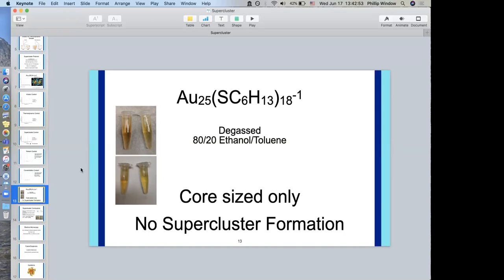So I think changing the actual nanoparticle core to something larger might reduce the effect that the charge state might have, because your counterion will be significantly smaller compared to the whole surface of it. In that case, I think the ligand would actually be more important than the charge state if you move to a larger nanocluster.